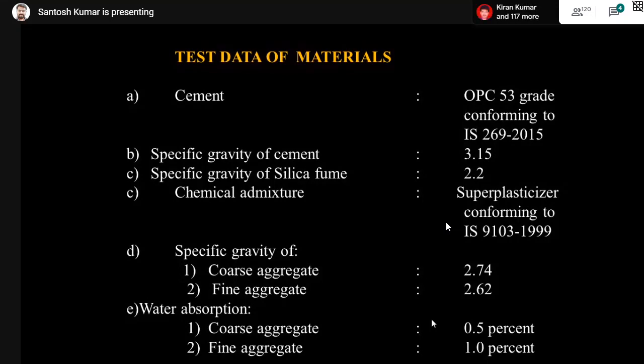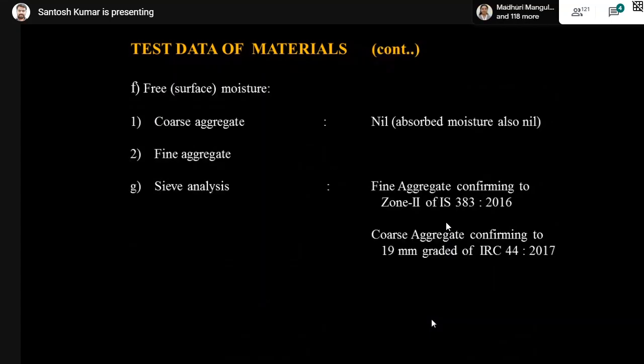If you are using crushed sand, the water absorption may go beyond 2 and 3 or 4% also. If you are dealing with basalt, especially in the region of Solapur in Maharashtra and Rajahmundry in Andhra Pradesh, there we have a lot of basalt aggregates. The water absorption of the basalt will be more than 3% and sometimes 4 also. The specific gravity also is around 2.9. So the absorption shall be taken in a proper manner.